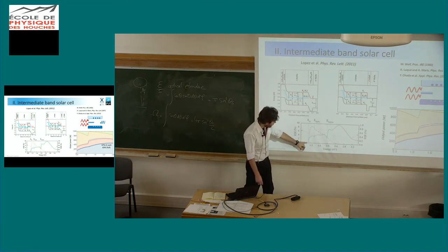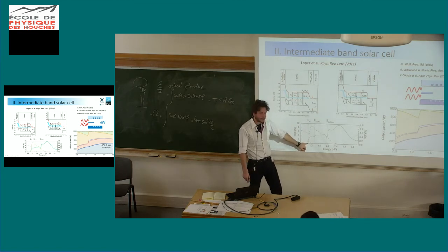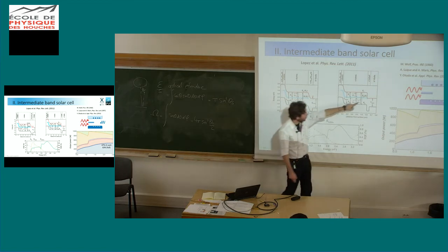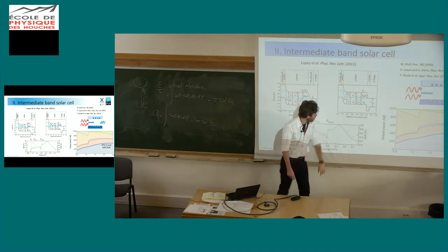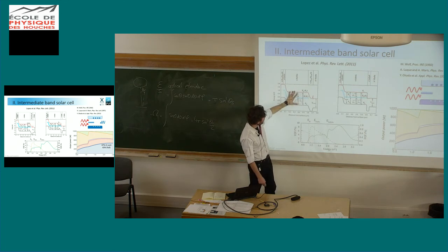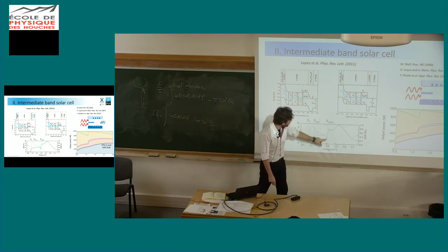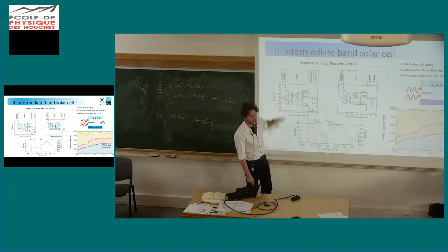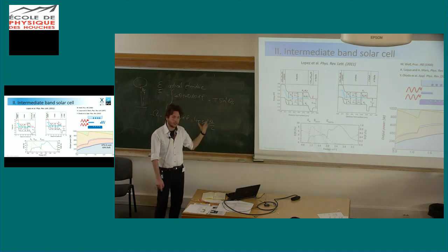For the connected band, the gap goes down to very, very low values, because essentially the gap now is here, where you'd like it to be there. While for the correctly disconnected structure, you have some absorption here, some absorption there, and you really see the gap here, which corresponds to the main structure. So there again, you do have experimental signatures of these things.